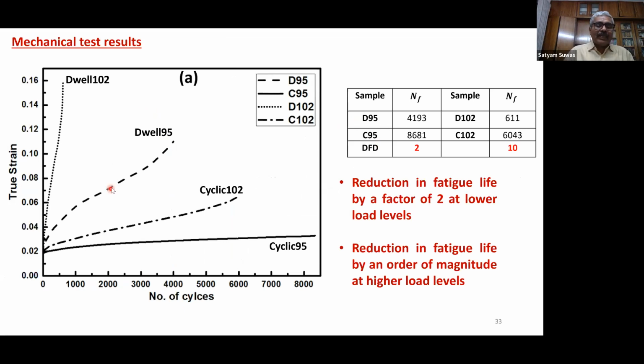So we followed that. And we could see, let's see, first the 95% loaded samples. Again, we compared for one particular sample. Here we have not taken the orientation aspect. We have just taken the as-received sample, and we could see that there is a difference between dwell fatigue response and normal fatigue for both the 95% of yield strength loaded sample, as well as the difference becomes far more if the loading stress is higher than the yield stress.